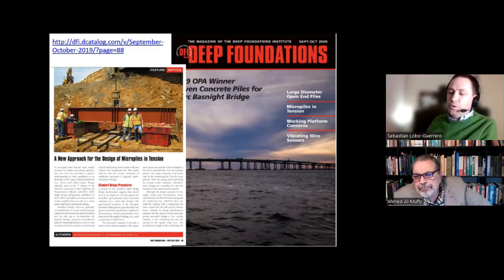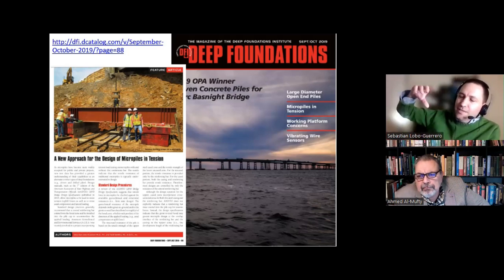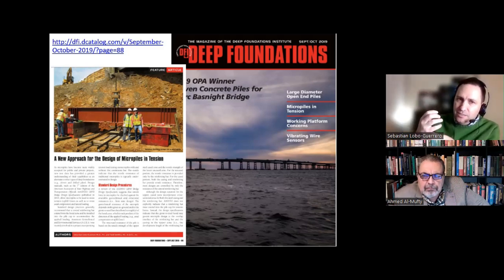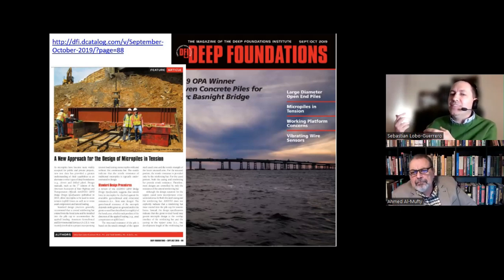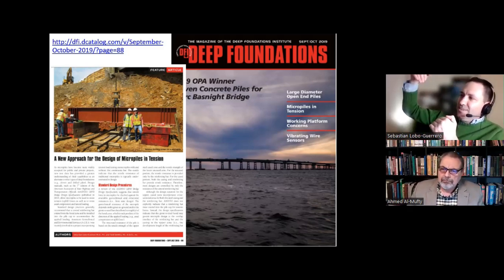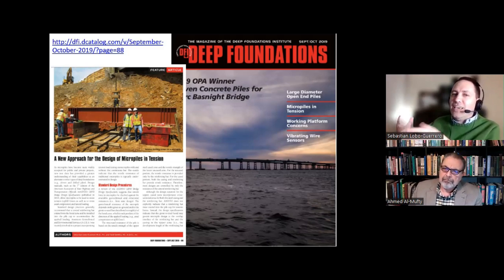A very interesting point that was brought to me, because we published this in the Deep Foundation magazine, and then we had a discussion on this at the DFI National Conference in Chicago, is that you've got to be careful. The theory works great, the tests show that it is great on small loads, but when you go to higher loads, remember, this is a threaded connection for casing, right? You've got to be careful that the connection on the threaded casing is able to take uplift forces. Typically, these threads on the casing are designed to take compression loads, right? So obviously, the casing is only as strong as the connection on the casing sections. If they were not manufactured on that part to resist the uplift, that's going to be the failure of your system.